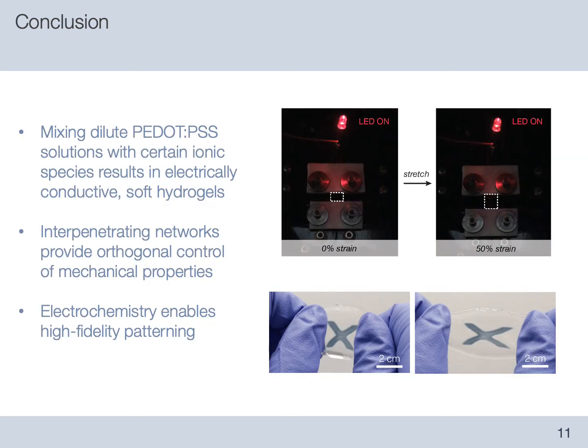To summarize, we have drawn upon our understanding of PEDOT:PSS solution properties and insights into the manipulation of PEDOT:PSS thin films to fabricate all PEDOT:PSS hydrogels that combine electrical conductivity with a high water content and therefore with tissue-level elastic moduli. We next use interpenetrating polymer networks to orthogonally tune mechanical properties like stiffness and stretchability. And finally, we used electrochemistry to create a new patterning method that will broaden the opportunities for this material to be used in next-generation bioelectronic devices.